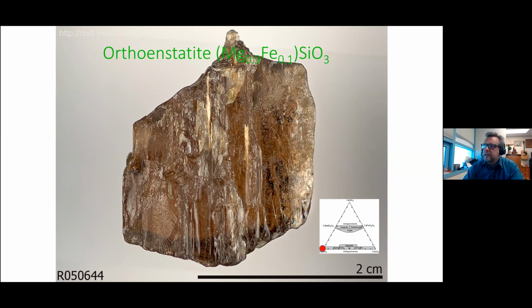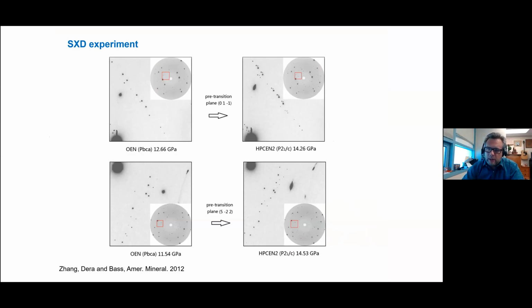We started with ortho-enstatite, which is an orthorhombic polymorph of MgSiO3. In this compositional phase diagram, compositions below 5% of calcium are typically orthorhombic, and above 5%, between 5 and 50%, are monoclinic. So this was an orthorhombic polymorph. This was work that we did in collaboration with Jay Bass and Jin Zhang, who then was a graduate student of Jay. This was early days of developing this single crystal technique for experiments going beyond 10 gigapascals.